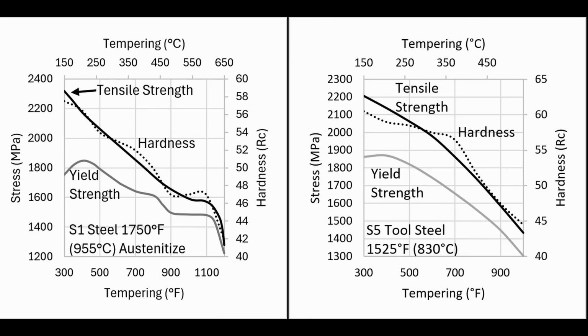And tensile strength and hardness are often well correlated, but yield strength sometimes is not as well correlated with hardness. So you can have a high hardness, but the yield strength, how much stress the steel can take before it deforms, is lower. And so you might be tempering very low to try to get a high hardness and a high tensile strength, but the steel is not as difficult to deform as you'd think it would be based on the hardness. And so if you temper a bit more, you get an increase in yield strength. The hardness and tensile strength does go down a little bit, and your toughness also improves. So this is why I give a minimum amount of tempering, because you want to increase your yield strength and gain more toughness. And so if you under temper, then that may not happen.